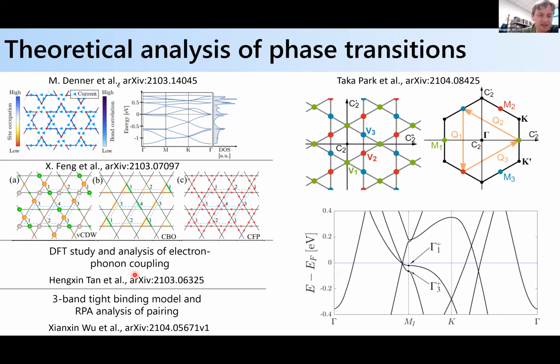For studies looking at the superconducting state, there's been some nice work analyzing electron-phonon coupling strength. I think the outcome was that electron-phonon coupling strength isn't enough to account for the TC that's reported, which suggests maybe you have unconventional superconductivity. Similarly, 3-band tight-binding analysis with RPA also suggests that you might have unconventional superconductivity, for instance, F-wave pairing. But this is all ongoing stuff. I think the superconducting state's not very well defined yet.